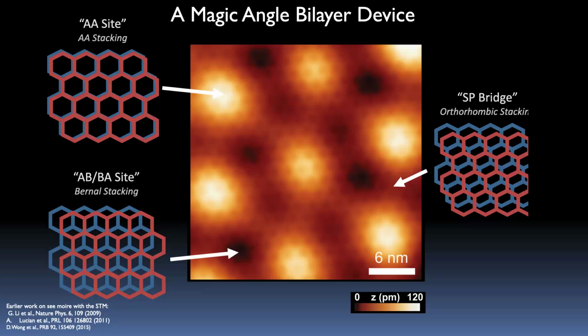Right away, let me just tell you, it's very difficult to make very big samples, because the way these materials are made is by tearing and stacking conventional materials. Stacking them, picking them up and putting them down, essentially involves polymers, and polymer is glue, which is very detrimental to any kind of atomic microscopy you want to do. Transport colleagues basically sandwich these things inside boron nitride layers. You don't really look at what's there, you just stick the leads on and make the measurement. We don't have the luxury of not knowing what we are imaging, because we have a microscope. So we have spent a lot of time to create extremely clean samples, as you see.